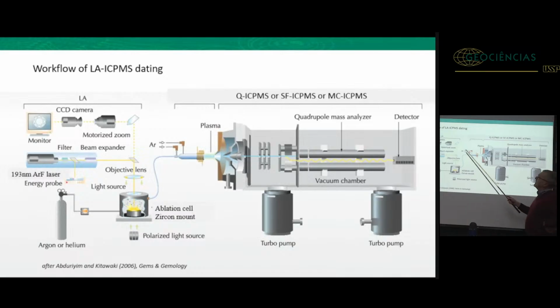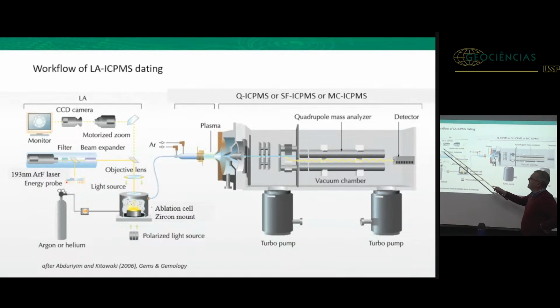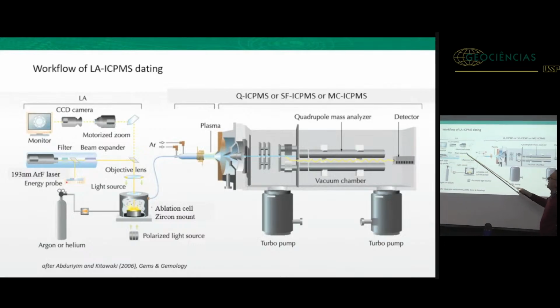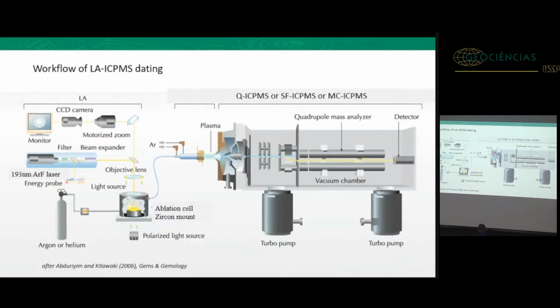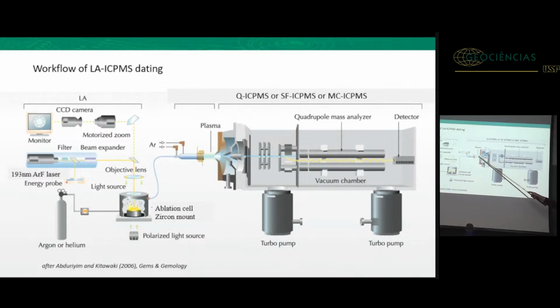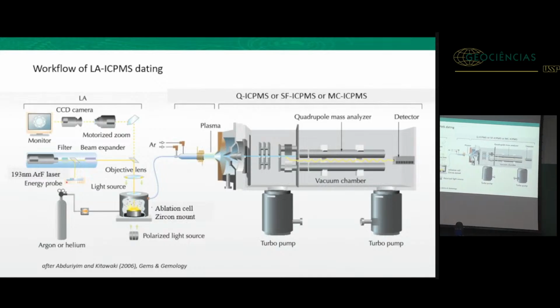And this is the workflow of laser ablation ICP-MS dating, which is fundamentally different. You know this probably also. We have a laser ablation, so we have a laser beam. Where is the laser? Here's the laser. We direct the laser onto our mount with our polished zircons. We ablate material, so there's really fragments ablated, which get transported by a flow of argon and helium into a plasma, 8,000 Kelvin, ionized, and then transferred from ambient pressures into a high vacuum into a mass spectrometer, where we analyze isotope composition. So this can be a quadrupole, which is shown here, Q, or a sector field ICP-MS, which would be an element sector field, single collector ICP-MS, or a multi-collector ICP-MS, a Neptune.